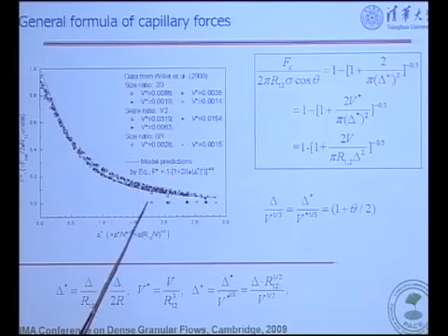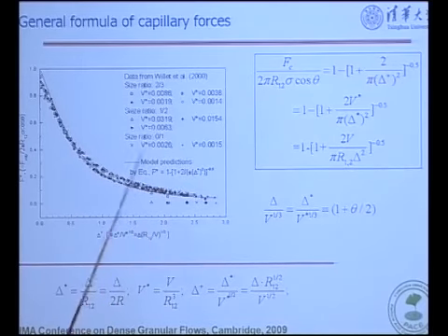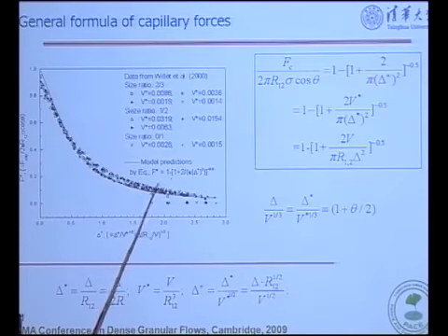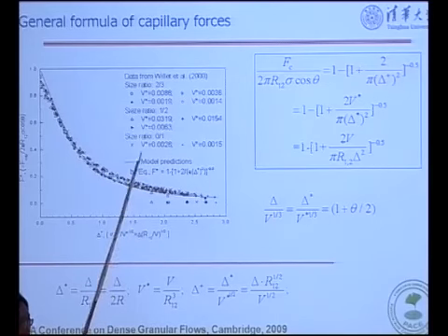And when I apply a scaling again, just like this scaling, we can find all the lines collapse into one for the liquid force. So we need to solve from experiment. We can use some similar theory, but we need to solve the Young-Laplace equation directly.